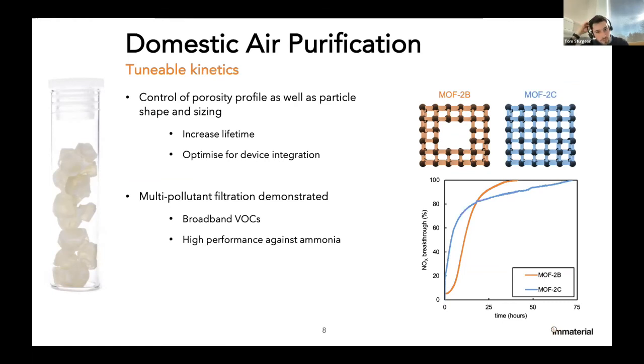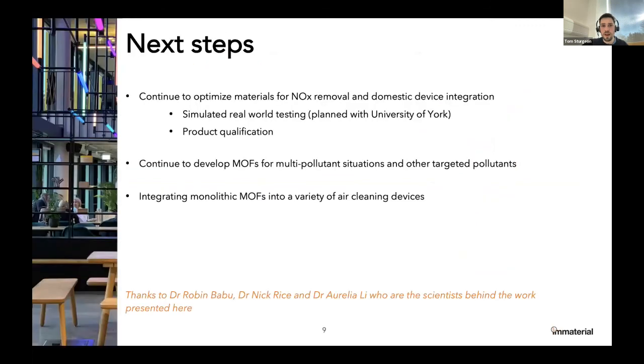So a bit more of the technology development. We can control the porosity profiles as well, and that's important for providing kinetics. Something else which has been mentioned today is the lifetime of these filters and how frequently you have to change them. So MOF2B, the orange one, was what I was showing you before. If we remove all the mesoporosity, we restrict the kinetics initially, and you get approximately the same total absorption capacity, but you spread that out over a longer time. So if you can tune these materials to give you a certain cleaning threshold, but then have to change the filters less frequently, that could be attractive as well in some of these air cleaning applications.